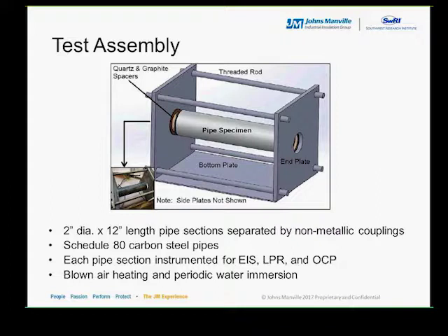For instance, the test method can be used for the following CUI test conditions: within the CUI temperature range defined per the NACE SP0198, within the CUI temperature range but below the dew point, within the CUI temperature range cycling it above or below, and above or below the CUI temperature range, cycling into it intermittently.